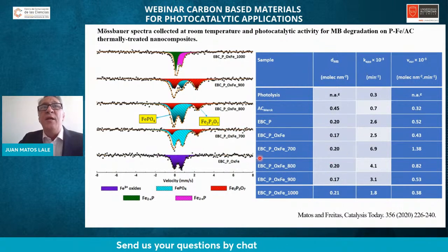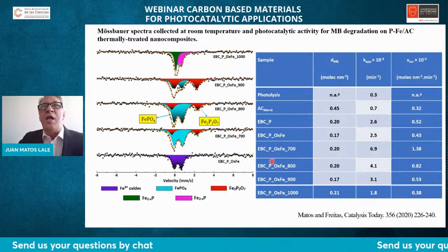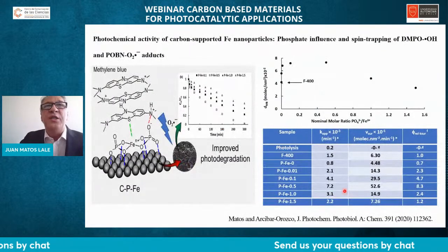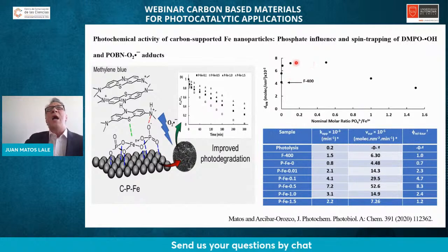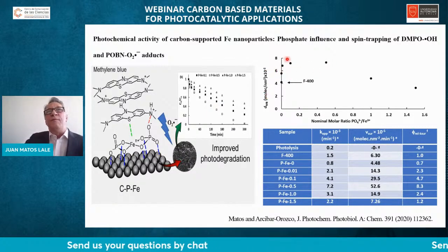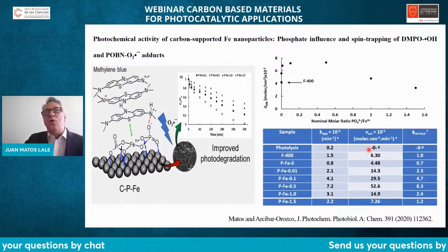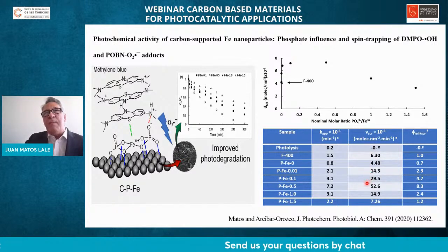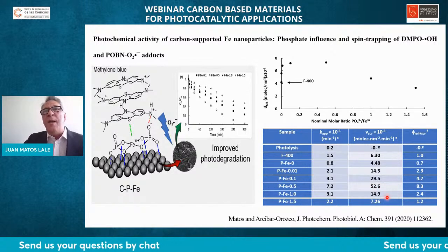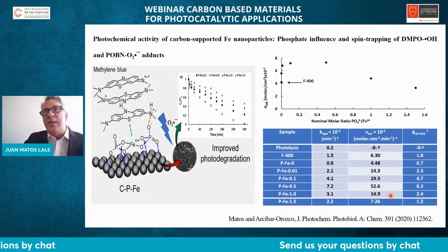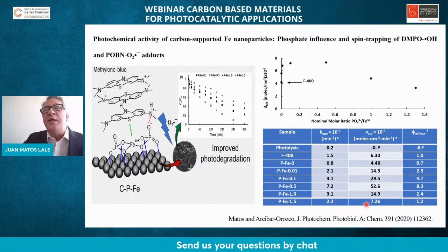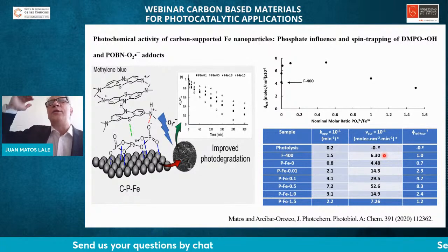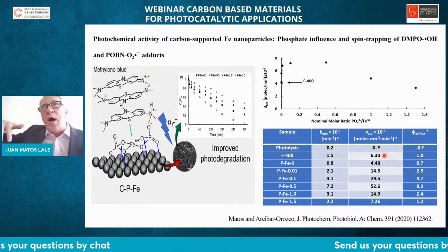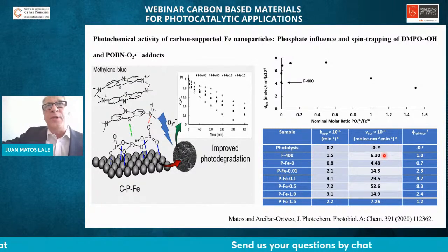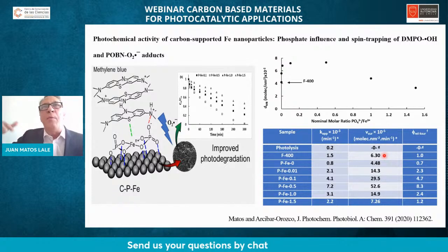So we optimized the phosphate in this range of temperature, and using this, we changed the quantity of phosphorus, and we achieved a maximum of molecular density for the adsorption of methylene blue, and a very interesting relationship until the formation of pyrophosphates. Once the phosphides are formed, the reaction decreases. So we need a high oxidation state in the heteroatom-doped, sulfur-doped or phosphorus-doped carbon-based materials.